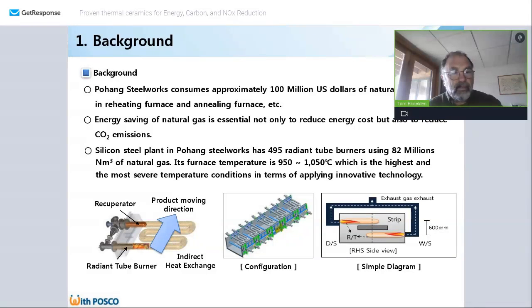Some pretty impressive numbers here. The Pohang Steelworks consumes about $100 million of natural gas in reheating and annealing, in their reheat and annealing lines. And therefore, in today's world of sustainability, reduced carbon, it's critical that they reduce energy and CO2 emissions. The silicon steel plant in Pohang Steelworks has about 495 radiant tube burners, using, again, 82 million cubic meters of natural gas. The furnace runs between 950 to 1,050 degrees Celsius, which is really, from my experience, pretty much on the extreme end of the lines such as this. So there was a strong motivation to apply new, innovative technology to save energy and reduce CO2 and NOx emissions.